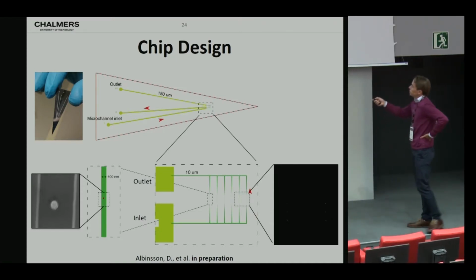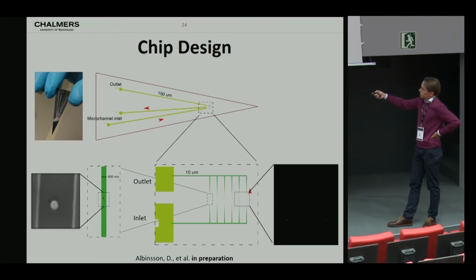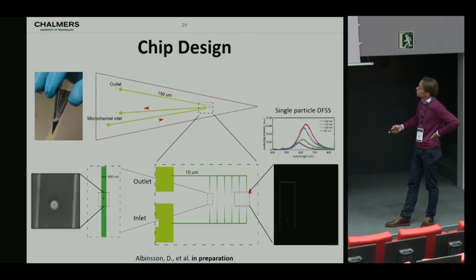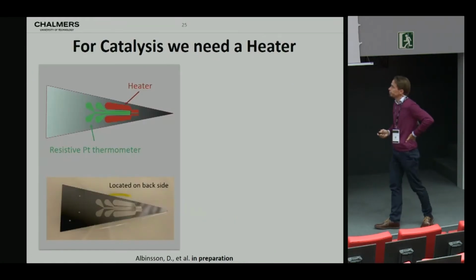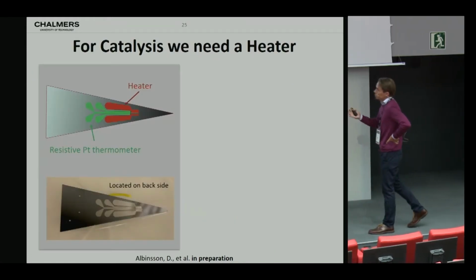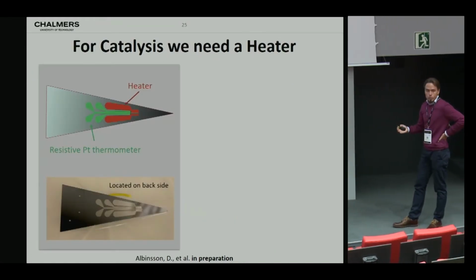We can then measure the dark field scattering image. Here you can hopefully see the signature of some particles in the channel, and for example, in this case, obtain the scattering spectra of 4 copper nanoparticles with slightly different size inside this nanochannel. Let me now highlight again, this is constructed for operation in gas phase, not with liquids. If we want to do catalysis and run reactions, we also need to control temperature.